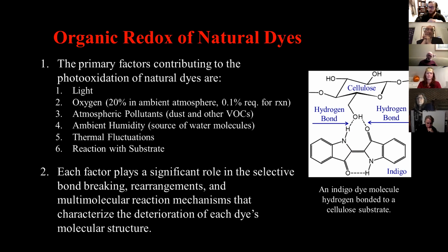The dust, which lands on objects constantly, we're constantly battling dust, whether it's in a private collection or a museum collection, can contain proteins, halides, salts, skin cells, combustion engine products, all kinds of stuff that's going to settle on a surface and act as a reagent in some of these reactions. So each one of those different factors can cause rearrangements within the molecule. It can break bonds, and it will generally lead to a characteristic deterioration pattern for each molecule. So while some random bond breaking does occur and random rearrangements can occur, it usually follows a particular pattern just due to the inherent structure of the dye molecule.